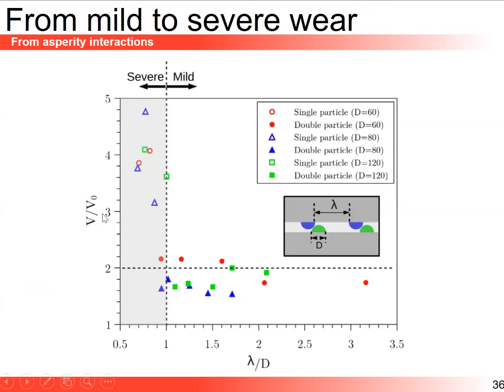So therefore, if you look at the total volume of wear mass that you produce as a function of lambda, the space in between the asperities, if lambda is large, basically larger than a junction size D, this is 1 on this axis, well, you will form two debris of volume V naught. V naught is the volume of a single small debris. So you have a 2 here on this axis. However, if lambda gets smaller than D, you transition to forming a severe wear regime where you form a much larger debris.